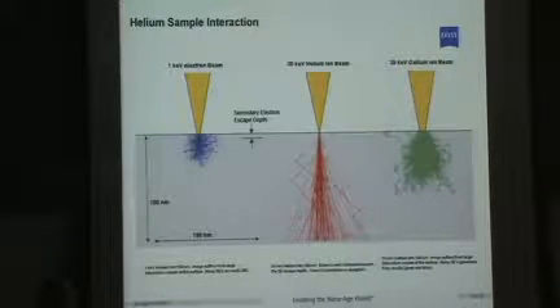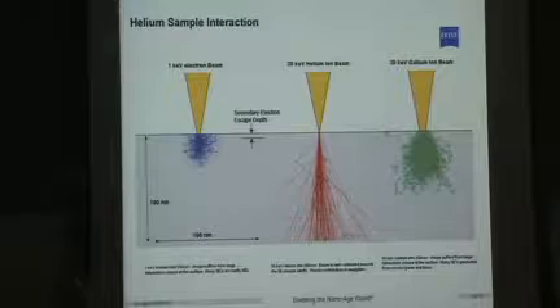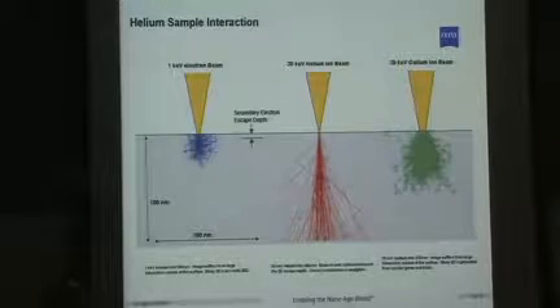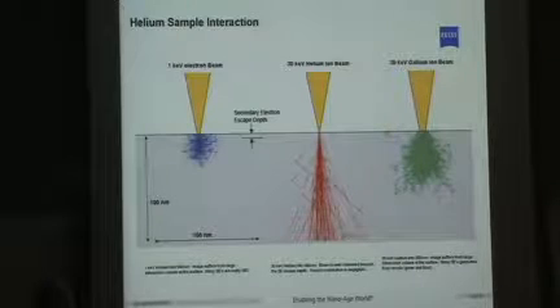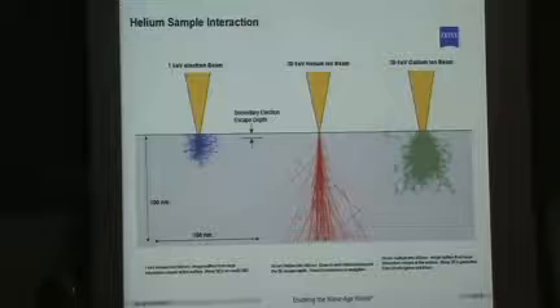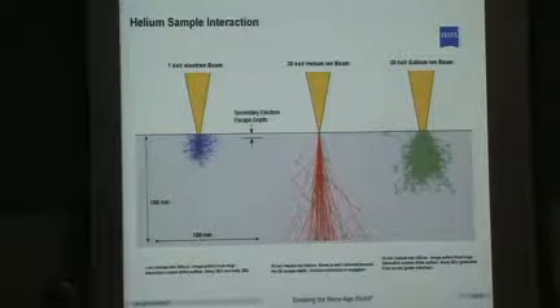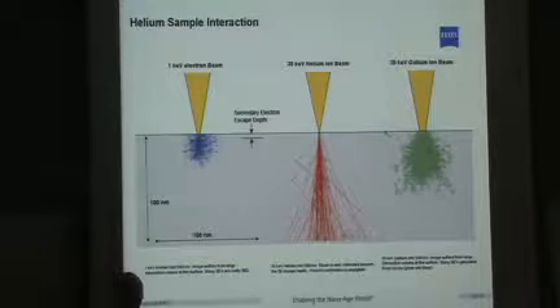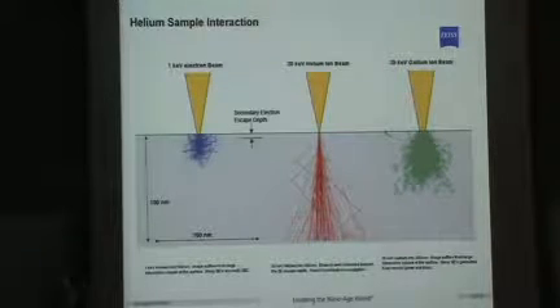The helium, being a little bit more massive, doesn't interact very well with the electrons. So as it goes in, it stays relatively collimated. And for reference, I've got what we call the secondary electron escape depth. It's a few nanometers for most materials. You'll notice the helium beam is still collimated over that length. So the electrons are coming out of exactly where the beam went in. So you can get a sharper image.